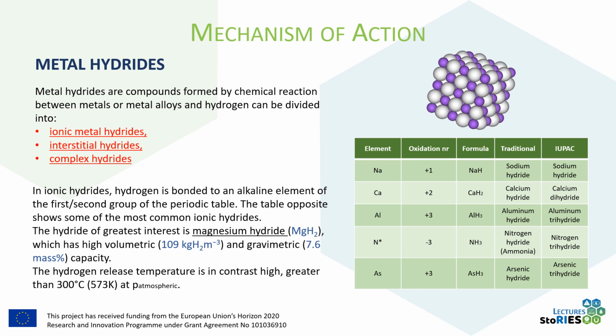Ionic hydrides are characterized by the bonding of hydrogen to alkaline elements from the first or second group of the periodic table. The accompanying table provides an overview of some of the most common ionic hydrides. Among these, we find magnesium hydride. It stands out as particularly noteworthy due to its high volumetric capacity of 109 kg of hydrogen per cubic meter and gravimetric capacity of 7.6 mass percentage.